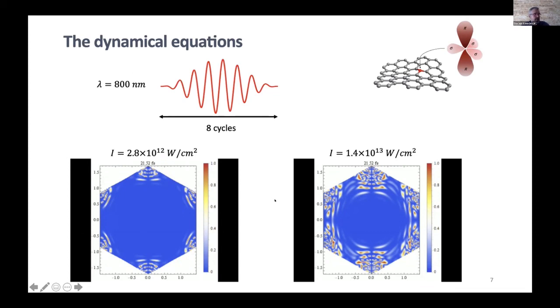Note that the population concentrates in regions near the Dirac points, creating interference fringes along the polarization direction, which grow as the pulse evolves in time. That is, the population is promoted to the conduction band near the Dirac points and then expanded to the rest of the band, quivering along the polarization direction of the field.